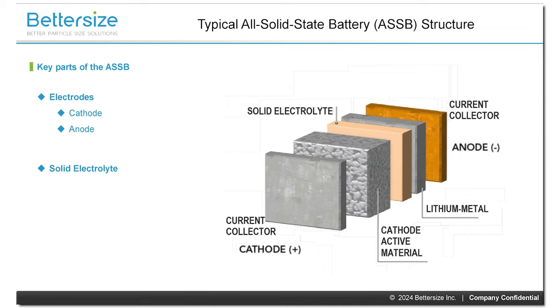There's a slight difference in the electrode materials, where the anode, the negative electrode materials in these solid-state batteries often include metallic lithium or lithium titanate or silicon-based materials. And this allows the energy density of solid-state batteries to be greatly increased. There's differences in terms of the interface characteristics, since now the interface contact of solid-state batteries is no longer solid to liquid, but it is solid to solid contact. And this means that there's a smaller contact area and higher interface resistance.